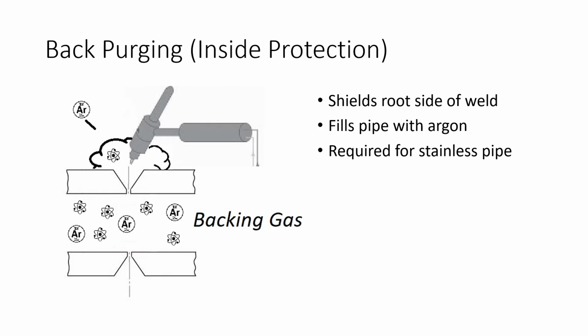It's going to shield that inside of the weld, which is still hot, and if it's liquid metal, it's going to come in contact with oxygen and nitrogen if we don't have that backing gas, that back purge, and it's going to sugar, and we're going to get that oxidation. So we put a back purge in there, and we'll fill the pipe with an argon or some kind of argon mixture. And this is how we're going to do it for stainless steel. Carbon steel, we can get away with not doing this sometimes, depending on our welding process and what's going on.